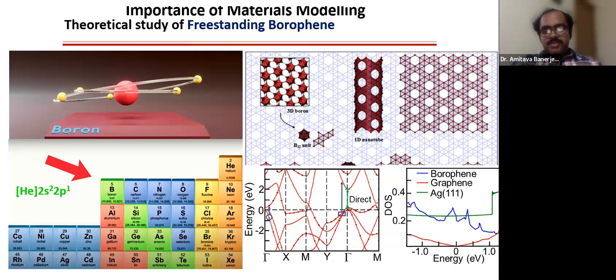So this is the reason for the anisotropy. Now that has a great impact on its optical as well as the carrier transport properties. If you're talking about the electronic structure as well as electronic materials, carrier transport is an important feature. If you examine the density of states of borophene and graphene, borophene is the blue line and graphene is the red line. You can see that there is a relatively large density of states near the Fermi level, which is at 0, in the case of the borophene monolayer, indicating a very high intrinsic carrier density.